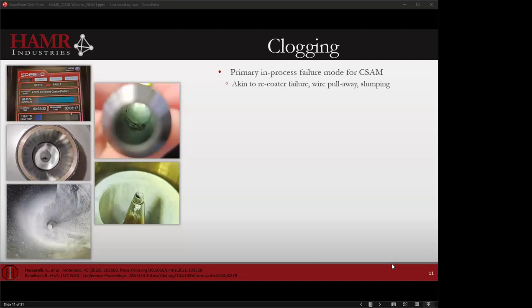The next issue that can challenge cold spray is clogging. We have different examples of clogging here. You can have clogging in a barrel, clogging in an injector, clogging in your powder feeder funnel, clogging in your nozzle. There's metal powder flowing, so there's a high probability that there's somewhere it can clog. And since we are primarily pneumatically driven, that is the biggest in situ process challenge that we face in cold spray.